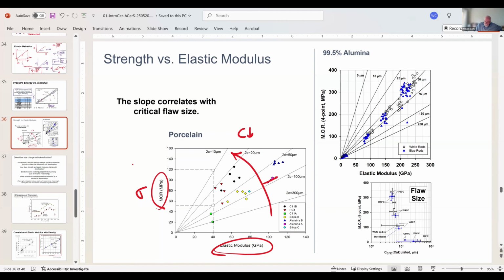As I go from bottom left to upper right, I am increasing my density, because I'm also increasing my elastic modulus. This is data for alumina, and there were two different alumina samples here. I've got blue and white. And you can see that they scale, and there is a small change in flaw size from 75 microns, roughly. It goes to 50 microns with densification, okay? So I get a small decrease in flaw size with densification, all right?